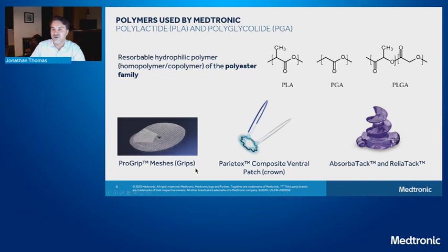ProGrip meshes have polylactide grips. That's 100% lactic acid, 100% lactide. Our Parietex composite ventral patch actually has a ring structure, and that ring structure is made of roughly 82% PLA and 18% PGA. Now, that same chemical composition is used in both AbsorbaTack and ReliaTack tackers. And many of the absorbable tackers that are out there in the market are PLA rich, around 80 to 85% PLA.